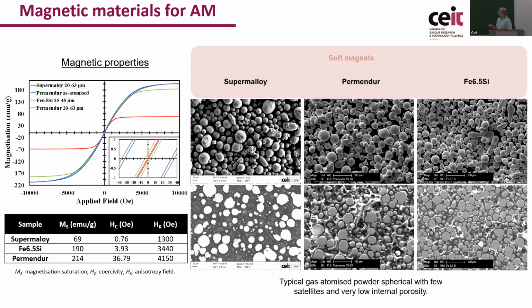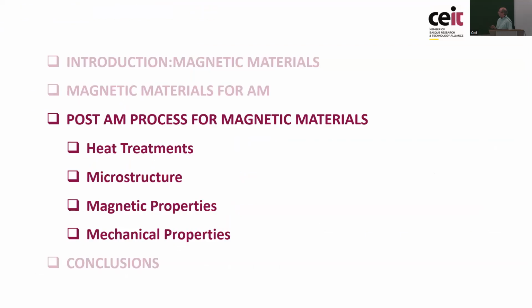And finally, the material with which we have worked is Permendur. The main characteristic of Permendur is that the saturation magnetization is very high, about 2.4 Tesla, which allows you to reduce the size of the motor. So it was a good choice. The coercivity is a little bit high compared with the other materials, but this is especially important when the frequency of operation of the motor is high. And I think this was not the case. So let's say the hysteresis loss was assumable in this project. So finally, the material of choice was Permendur, and now Miren is going to explain the work that we have been doing with this material.